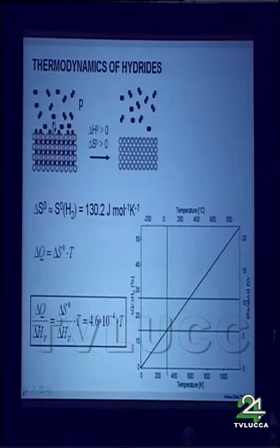Now, thermodynamics tells us, besides the plateau, a second important parameter, and that is the heat evolved during the absorption or desorption. And this heat, delta Q, is the standard entropy of hydrogen times the temperature. And if we put this heat in relation to the heat of combustion, the higher heating value of hydrogen, then we find this simple relation here, that the ratio of the heat necessary to desorb the hydrogen divided by the higher heating value is 4.6 times 10 to the minus 4 times T.